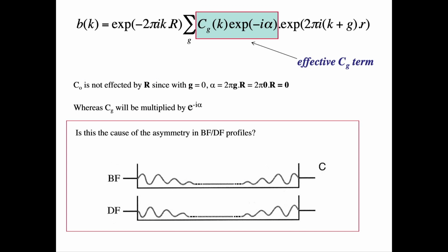And as metallurgists we're feeling pretty clever now, right, that we've understood these differences by using the dynamical theory, but coming out with physical ideas of what's happening. We always go back to physical metallurgy. So we have physical ideas that, all right, we can see in a diffraction pattern, say, two beams. We know then they're two Bloch waves. We know that one of them is highly scattered, and so we can understand some of these fringing effects, and then as we deviate positively from Bragg, why we lose the fringing effects, and so on. So we're doing pretty well. And that is the end of the story.